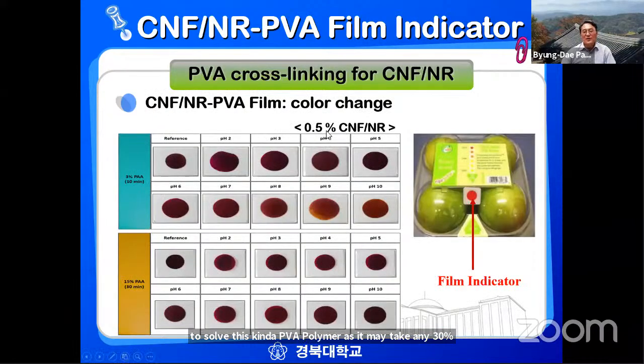Here we use 0.5% CNF and the neutral red, and then 3% PAA and 15% PAA at different times. I just showed examples. These have different colors depending on the pHs, and at about 15% there is not much color change because they are very highly cross-linked. So the idea is something like this: we're going to have this kind of film indicator for food or something.